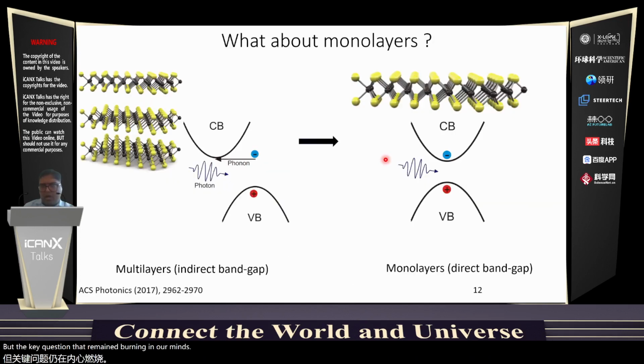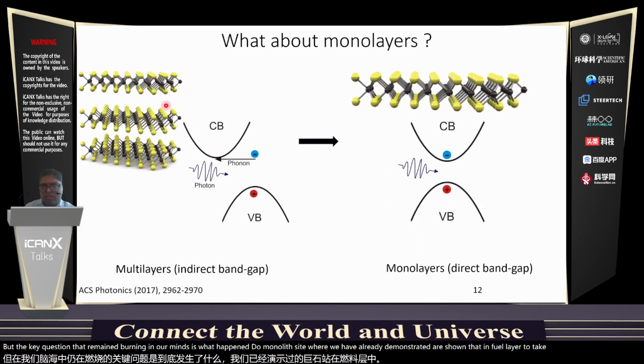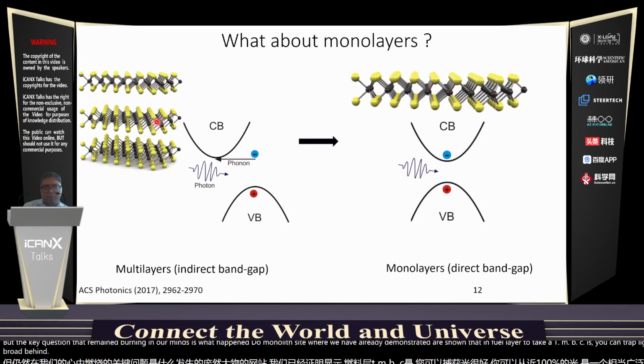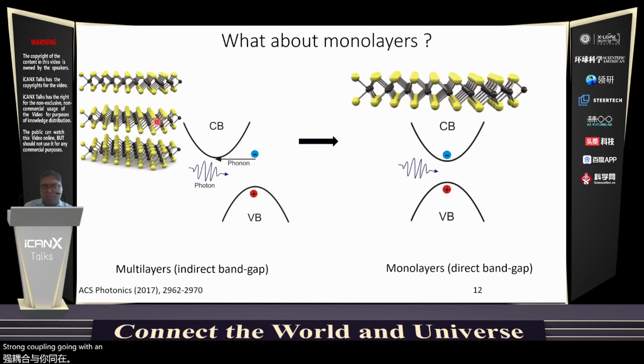But the key question that remained burning in our minds is what happens to monolayers? We have already demonstrated that in few-layer thick TMDCs, you can trap light really well. You can trap nearly 100% of the light over a fairly broad part of the spectrum, especially when there is strong coupling going on between excitons and photons. But it is also well known that few-layer TMDCs are indirect band gap in nature. As opposed to that, monolayer TMDCs are direct band gap in nature, and they can also emit more light.